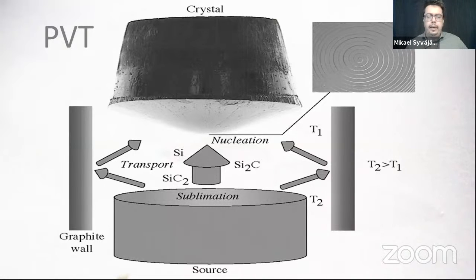Now, my field of research is silicon carbide. At that time, we explored the bulk growth of silicon carbide. So this is the physical vapor transport. In that one, we have a powder source of silicon carbide on the bottom here. And when we heat it up, you have silicon and carbon bearing species which are formed, and they are transported to the growing surface by a temperature gradient. So it's colder at the growing surface than at the source, and the vapor species are then transported there. So this is the physical vapor transport method.